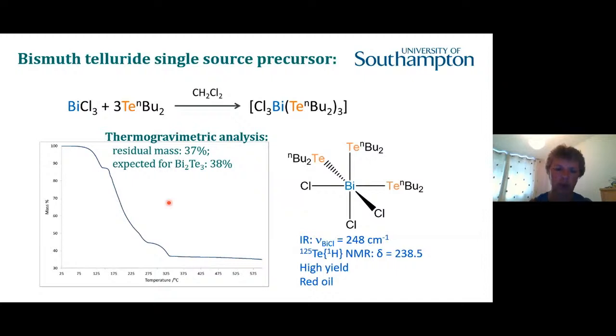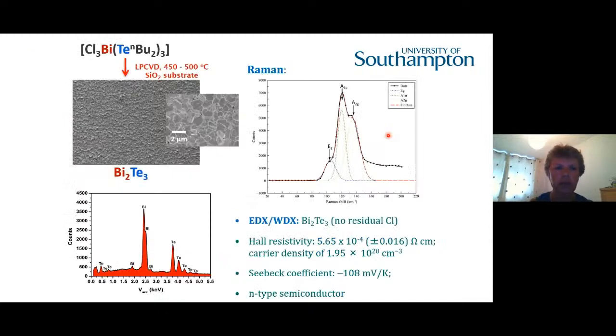And by looking at the thermogravimetric analysis, we can actually see that under these conditions, as we increase the temperature, we drive mass loss. And the final stable mass that we end up with is fairly close to the mass we would expect for Bi2Te3. And so that gave us encouragement that this precursor might be a good reagent for CVD experiment. So we went on to look at that CVD experiment using the equipment that I've shown you.